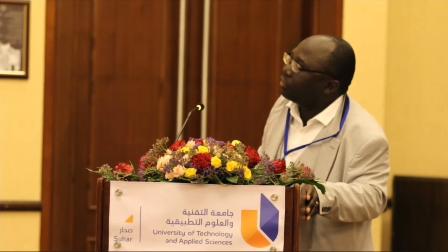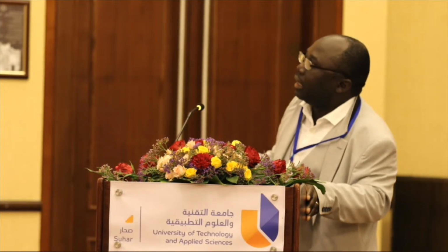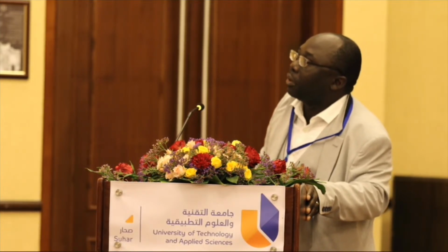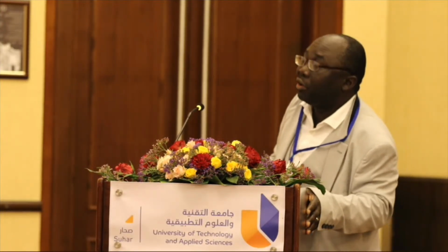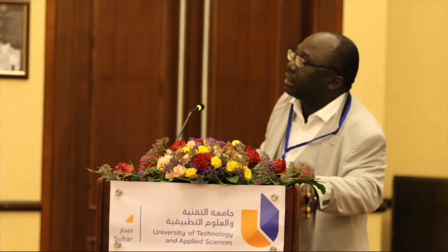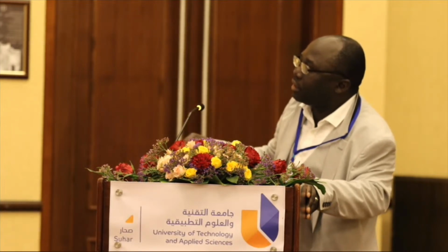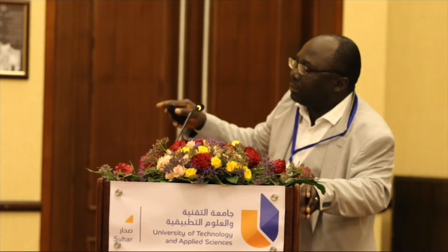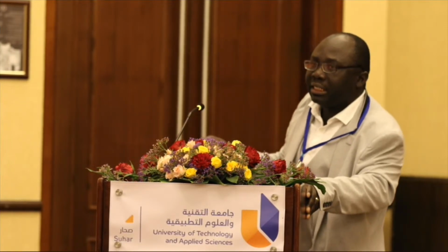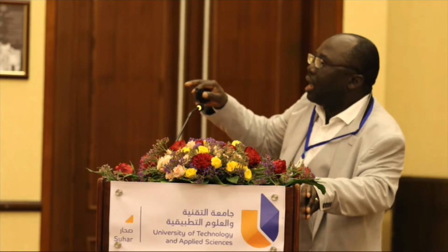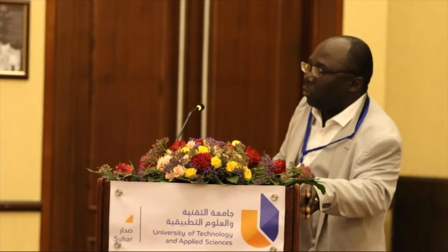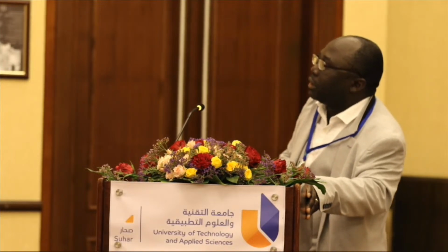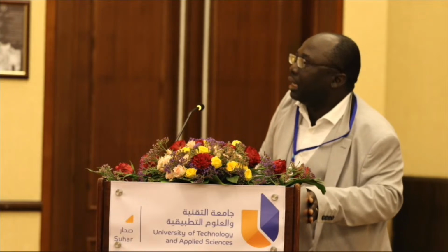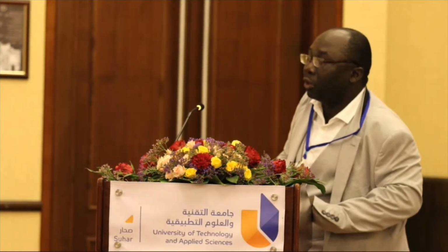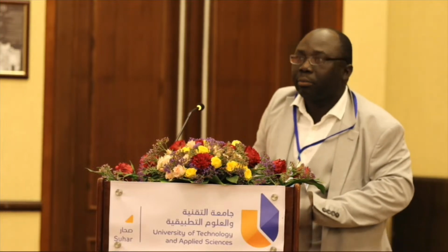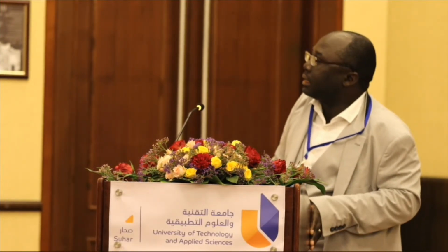The other way to transport hydrogen is to transport hydrogen as liquid hydrogen. As liquid hydrogen, you transport hydrogen at a cryogenic temperature of around minus 253 degrees C. Again, this is very expensive, and as you can see from this figure, this is a concept liquid hydrogen storage tank from Linde Engineering in Germany, and you can see, just by looking at it, how complicated it looks. But interestingly, transporting hydrogen as a liquid is way cheaper compared to transporting hydrogen as a compressed gas.